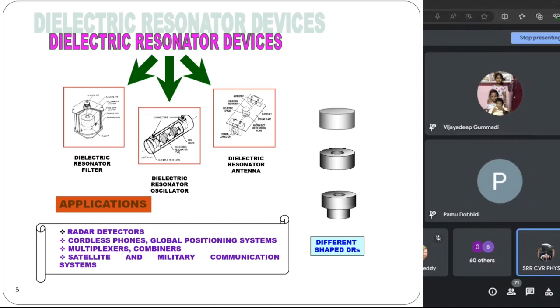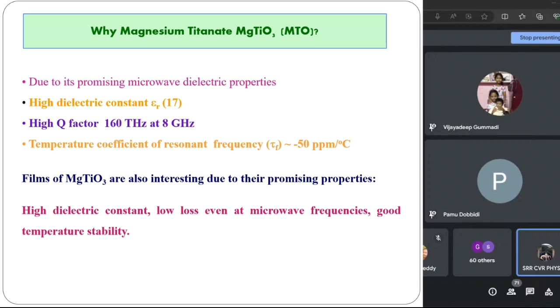Can you go to the next slide? Yeah. So as I told you, why did we choose this material? This material seems to be very simple. You just take magnesium oxide and titanium oxide and mix them. You should get, in principle, magnesium titanate. But it is not a simple material because it is a hygroscopic material. The moment it sees some kind of moisture, it immediately forms a secondary phase called MgTi2O5. So as a result, even though this material seems to be simple, it is not very easy to process. That is where we took this material as a challenge to propose for a space application.